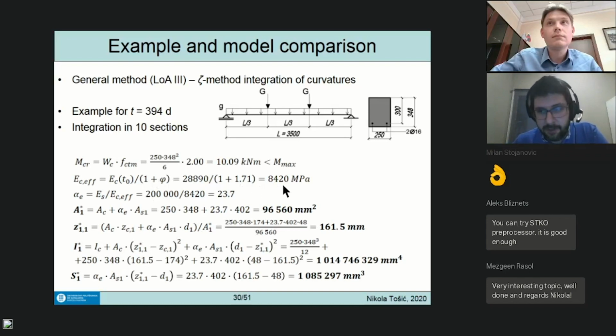We see that the effective modulus is about 2.7 times smaller. The modulus ratio is now 23.7, so the steel modulus over the concrete effective modulus. Now I have to calculate certain geometric quantities.